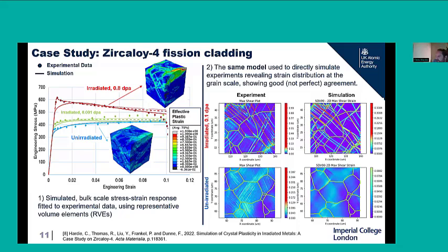And these experiments are just tensile testing, so the same type of testing, but instead of worrying about stress strain, we're looking at the strain heterogeneity in zircaloy 4 that's measured by high resolution digital image correlation. So we can see the bottom row is unirradiated and the top row is irradiated. The striking difference in the strain heterogeneity, so strain localization, is a big difference after irradiation. And on the right column, we can see that the simulation, to some extent, represents what we see experimentally without changing the model. So this gives us confidence. It's not perfect, but it gives us confidence that this might be the correct modeling platform to use to develop predictive capabilities.